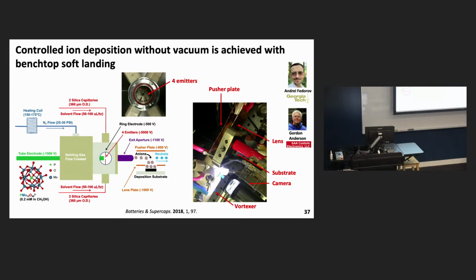And then we increased the gas pressure at which we run this, and used heated gas. The idea of this device is it creates a vortical flow of gas which converges right at those electrospray emitters. So as you're producing your charged droplets of whatever you want to deposit, you have this high density of highly agitated gas that comes in there and strips any solvent from around those ions. The pressure then drives those out into the laboratory environment. We have a pusher plate which turns them 90 degrees and a lens which gives us some focusing. And then these are deposited on substrates.